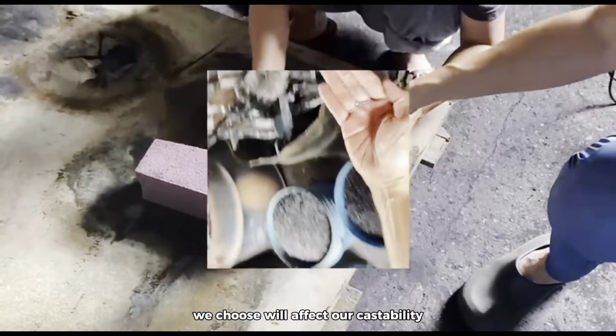However, if the ventilation is insufficient or becomes blocked, the gases cannot escape properly. Additionally, if the pouring rate is too fast, the molten metal can seal off the air passage before the gases have a chance to exit, causing them to become trapped. Once the metal solidifies, the trapped gas forms small cavities known as blowholes. They weaken the mechanical strength of the final product and may cause surface defects.